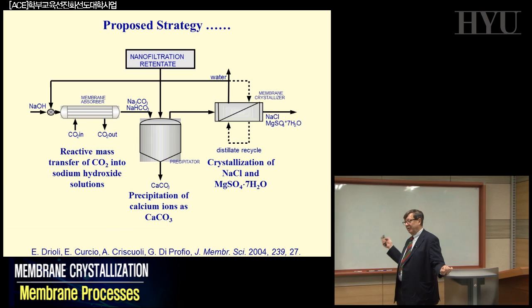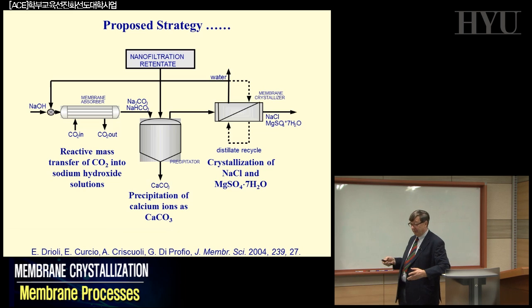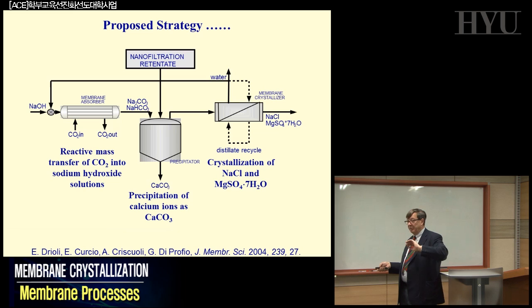It's not just this, it's the product of the concentration and the square of the charge of the ions forming your system. And that's a strong effect on the final performance. And so what has been suggested already a few years ago, as in the nanofiltration, is first you precipitate all the calcium, because calcium otherwise is the first one to be saturated and to be crystallized.